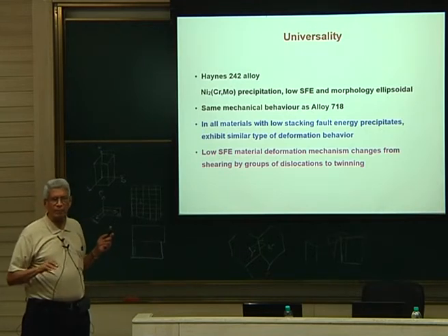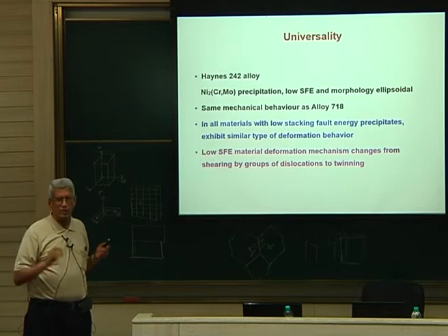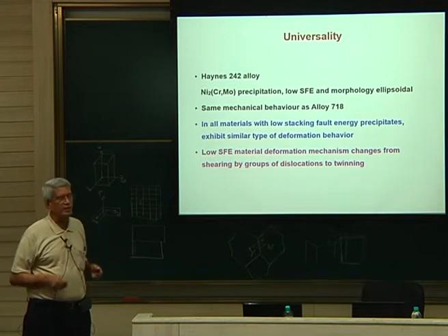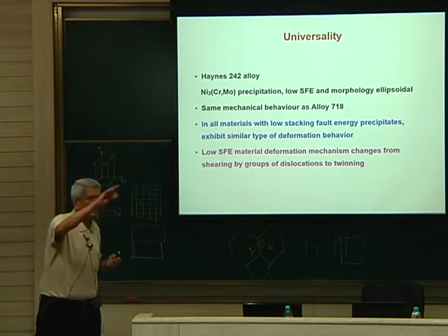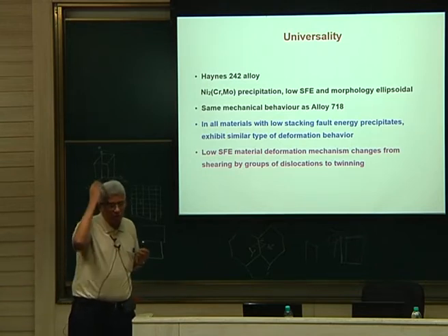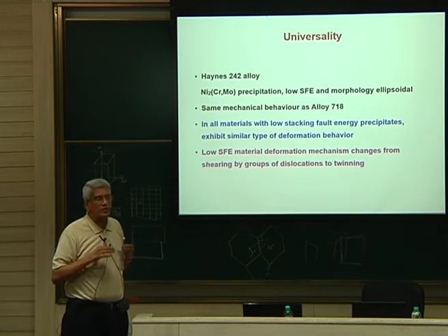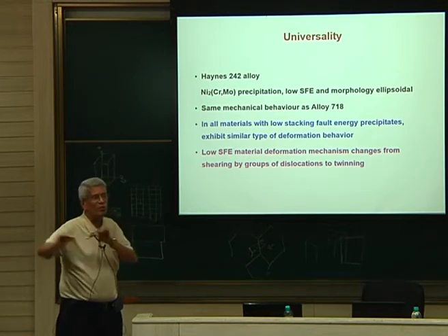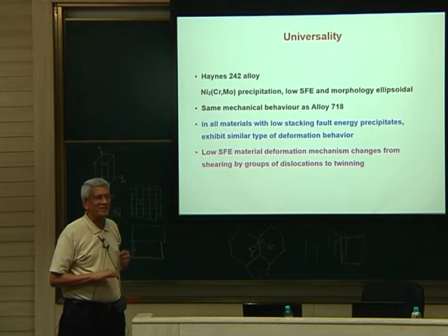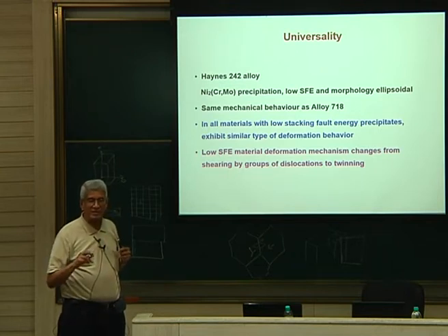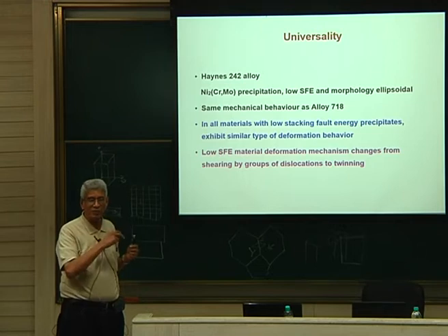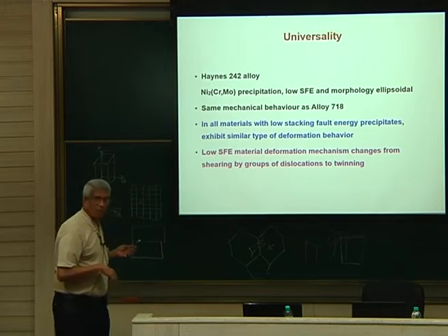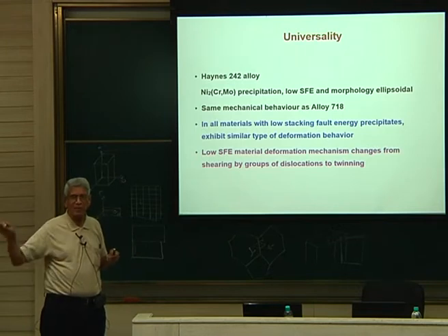You know that whenever dislocations are there and dislocation interaction is very prominent, the work hardening rate will have a large value. You know what the characteristic of a twin is? The stress which is required for a twin to form is very high, but once a twin is nucleated, if it does not see any obstacle, it will go from one tip through and reach the other end at the grain boundary. So when such a process happens, the work hardening value will come down. But afterwards it goes up because intersecting twins will come; that is a different phenomenon.